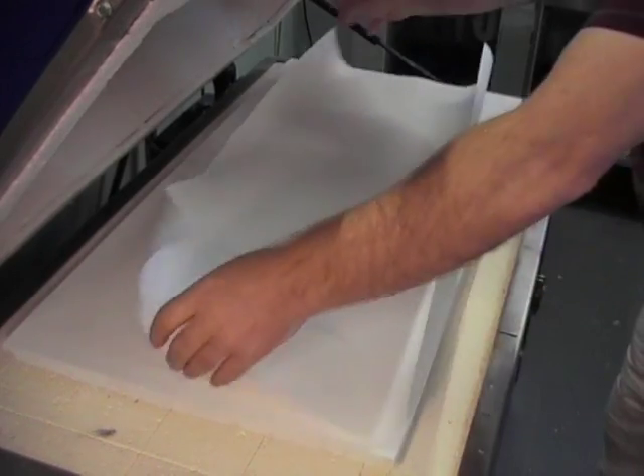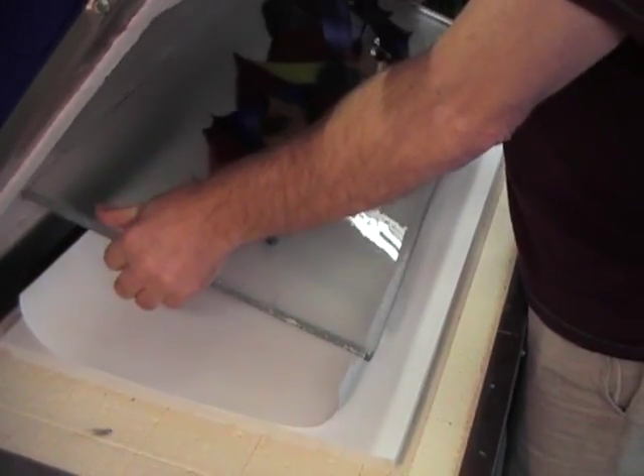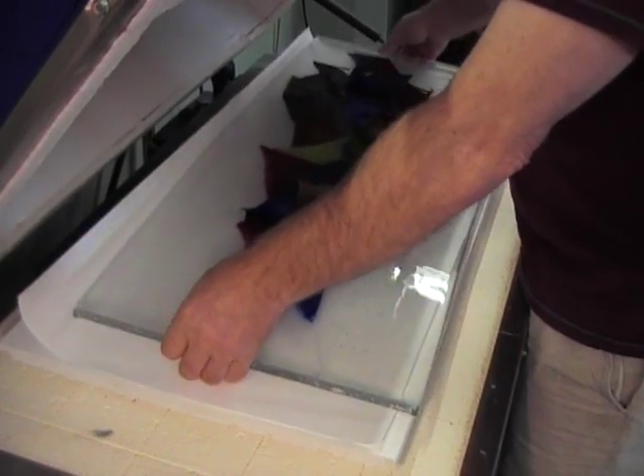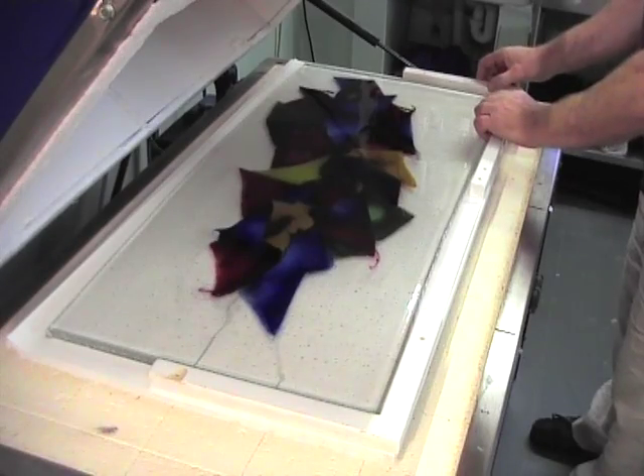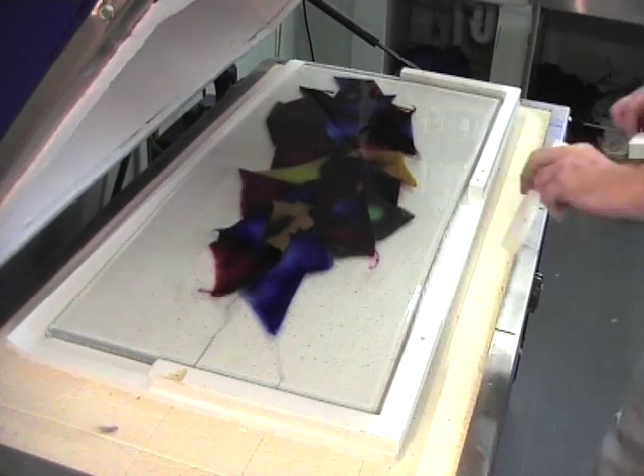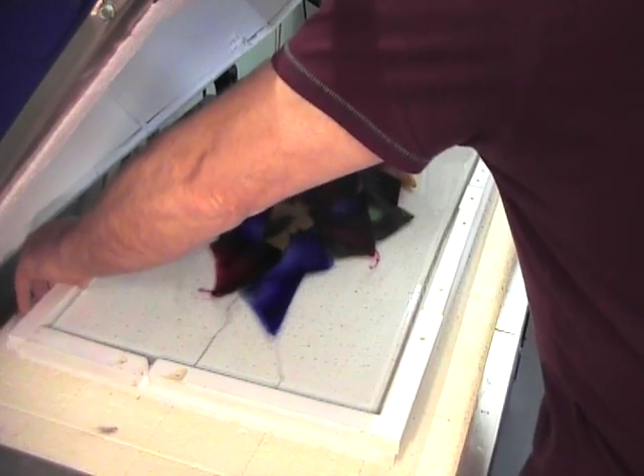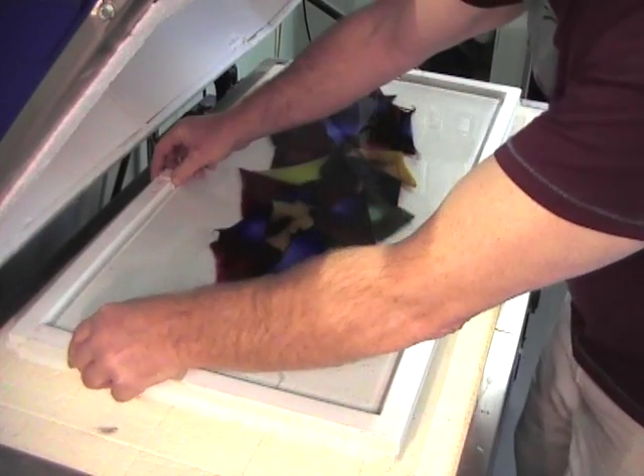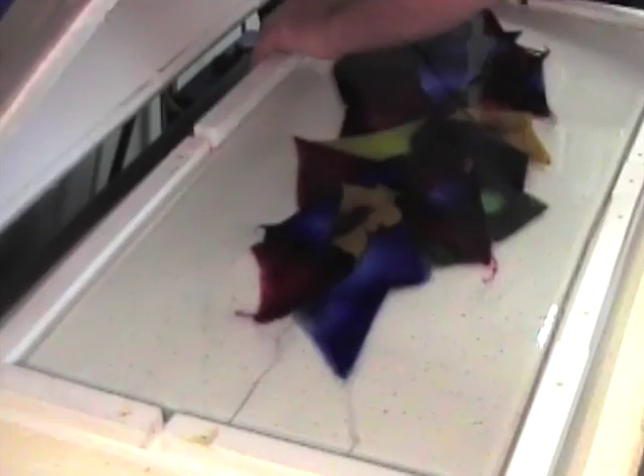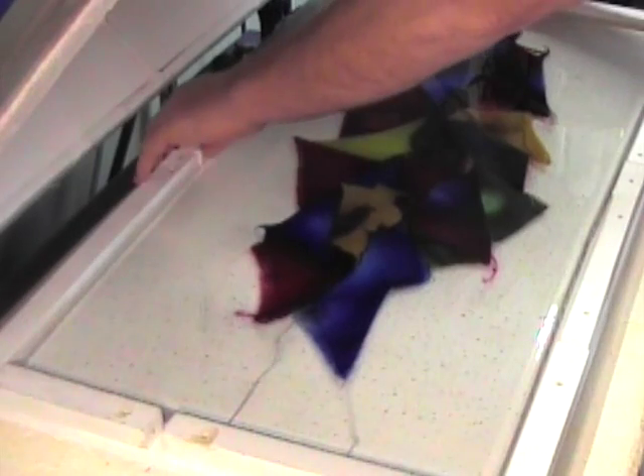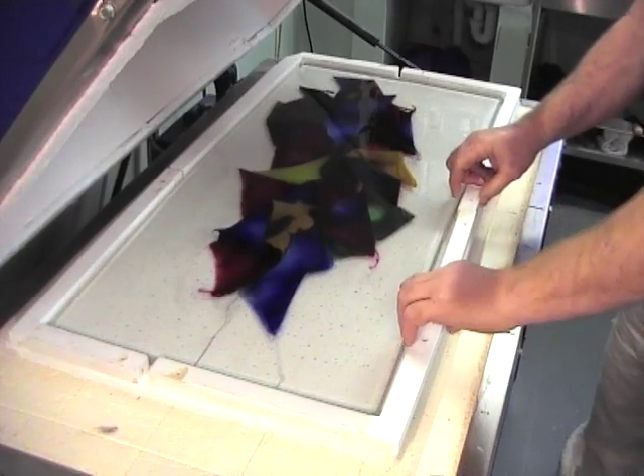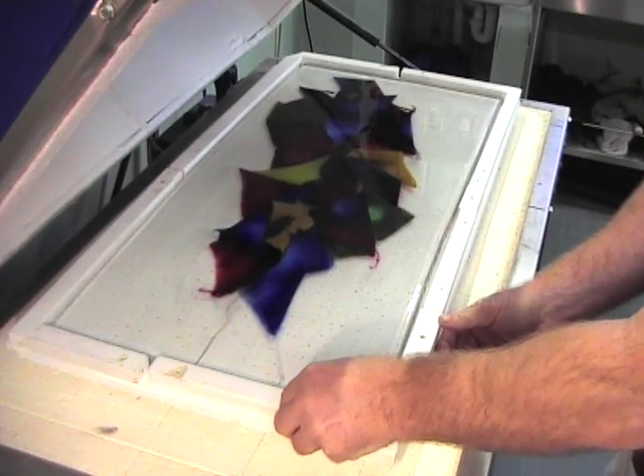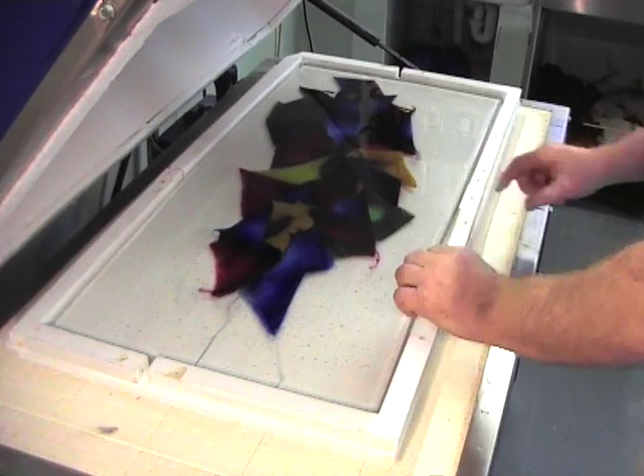The kiln shelf and hot dams. Because of the high temperature needed to rake glass, it is important to protect the kiln shelf with both kiln wash and Bullseye thin fire paper. Once you have positioned the work onto the kiln shelf, you need to construct a dam around it to constrain the work and prevent the molten glass spreading. At 910 degrees centigrade, glass takes on the consistency of molasses and will flow very easily. The raking action itself will also create an almost slow motion tide effect, which will spread the glass out. It is therefore imperative that a stable dam is built.